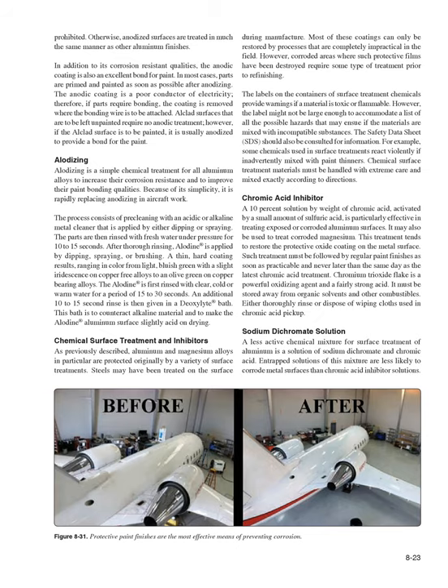A thin, hard coating results, ranging in color from light, bluish-green with a slight iridescence on copper-free alloys to an olive-green on copper-bearing alloys. The Alodine is first rinsed with clear, cold or warm water for a period of 15 to 30 seconds. An additional 10 to 15 seconds rinse is then given in a deoxylyte bath. This bath is to counteract alkaline material and to make the Alodine aluminum surface slightly acid on drying.